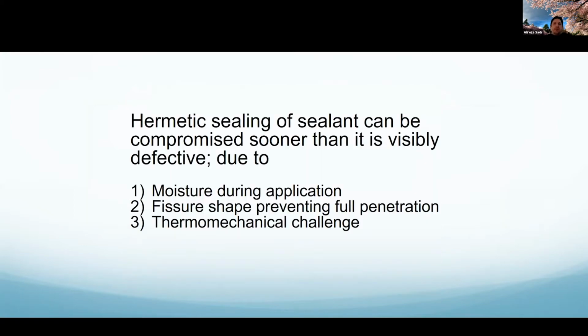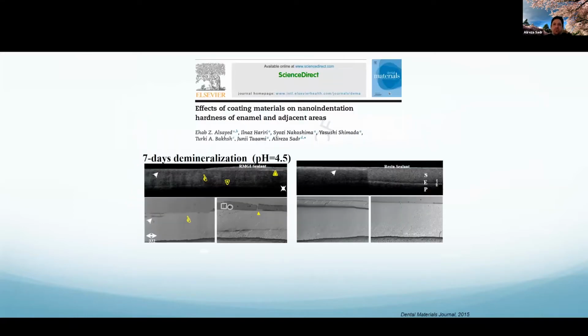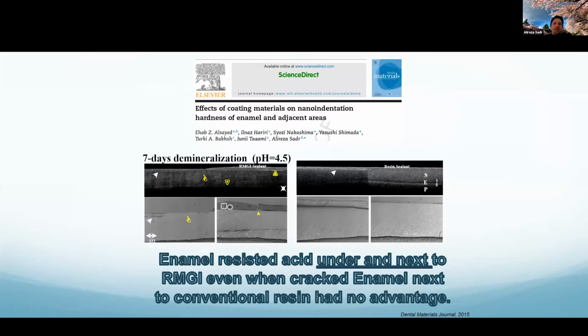Because they fail locally. So the question here is, if we can't really seal with a sealant, then what should we do, right? So we did look at the nano indentation hardness around the sealants. And what I want to tell you here, I'm going to go quickly. If you have a resin modified glass ionomer or a glass ionomer-based sealant, you have advantages of increased hardness and increased acid resistance around the sealant. And that's a great thing, right?